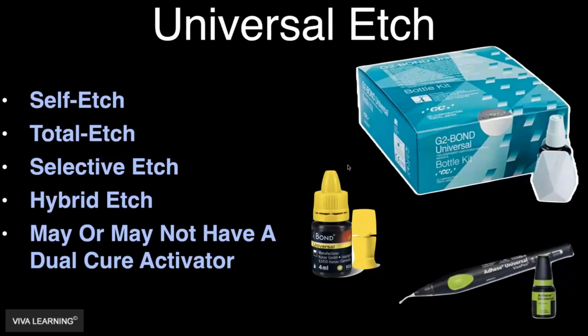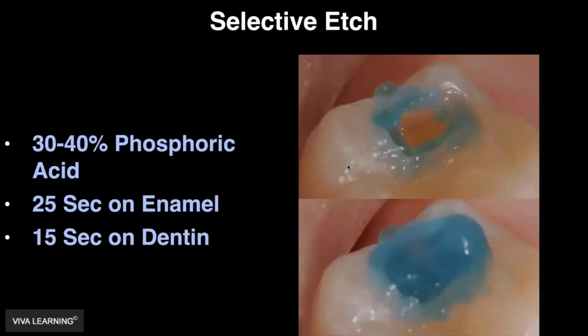So not only do they give us the clinical advantages, but they also give us advantages thinking about it from an inventory control perspective. So for some of you, you may be thinking four etching techniques. So let's talk about what they are. So I've already defined total etch. Total etch to me is 35% phosphoric acid, cover the entire prep of the tooth, and let it go for 25 or 30 seconds. When we do that on a preparation that has a high percentage of dentin that's exposed, you are going to risk over etching that dentin. That could increase sensitivity. It actually can decrease initial bond strength. So there's lots of reasons you don't want to do that.